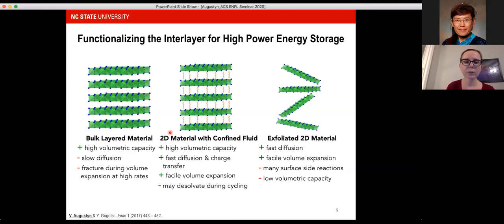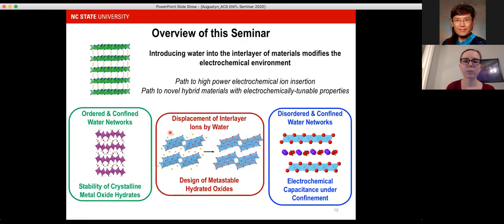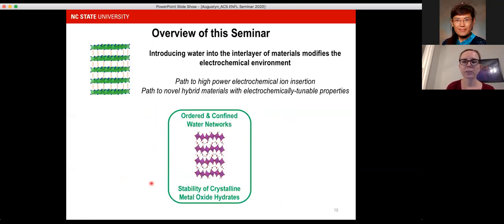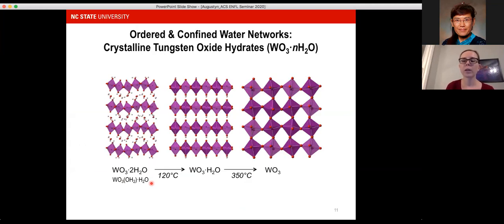And so the first story on the ordered and confined water networks was a natural place to start, because we wanted to work with materials where the water was confined, where the crystalline structure was already known. And so we picked as our model material these crystalline tungsten oxide hydrates that you can precipitate from acid solutions at room temperature, what are also called tungstic acids.